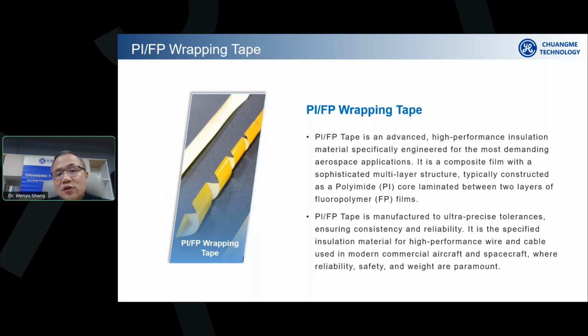As I said, the core is the PI polyimide, right? And then we put two FP layers on both sides of the PI film. FP stands for fluorine polymer, right? We take a specialty fluorine polymer and coat a very thin layer of it on both sides of the polyimide film, and then we cut the film into a narrow tape. And then we wrap the tape onto a wire, as I just explained.